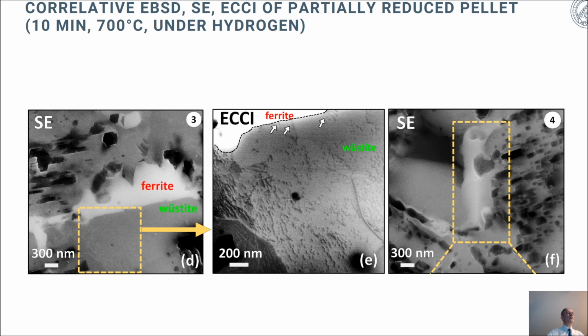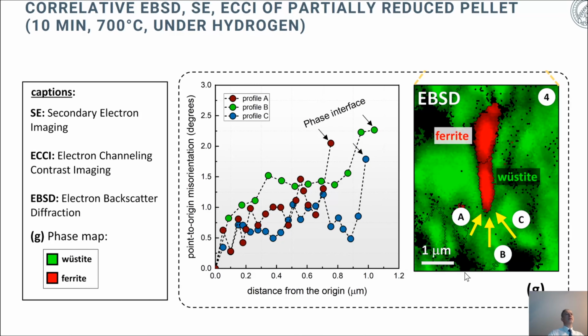That means we must, for interpreting the kinetics of the reduction, also consider the formation of internal defects both inside of the wüstite and ferrite. The reason for that is again that the volume mismatch between the two is very high and leads to substantial stresses and also to fracture. This is also shown here again, where in the secondary electron image you see again ferrite forming in the wüstite, and here in the wüstite you see everywhere this very fine porosity which builds up. This is, by the way, also very important, because when hydrogen can diffuse to these open pores from the outside, then the outbound diffusing oxygen from the reaction interface can already recombine in these pores to form water, which is also a very kinetically important aspect.